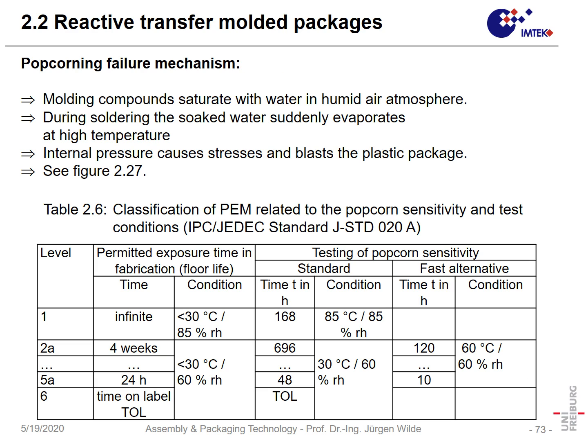And the idea behind the test is the following. We define a so-called popcorn sensitivity level. That level can go from 1 to 6, and that level defines how long you are allowed to expose it on a typical fabrication floor. For instance, if you have in your fab temperatures under 30 degrees centigrade, but 85% humidity, that could be somewhere in China, Southeast Asia or so. And when you are able to keep this package for infinite time in such atmosphere and without coming to popcorn effect afterwards in soldering, then the package gets the best level, which is level 1.